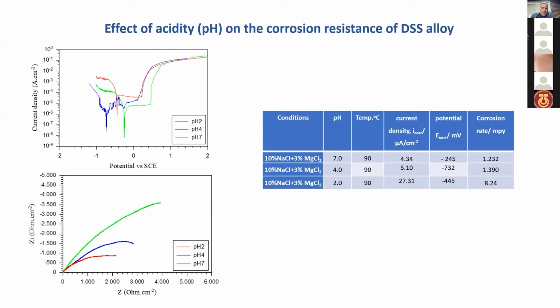Now we go to the second parameter, the effect of the pH or the acidity on the corrosion resistance of the duplex stainless steel. It was reported in a previous study that the corrosion in the magnesium chloride solution is higher than the sodium chloride due to the relatively high viscosity compared to the sodium chloride solution. And because of multiple operating environments and to cover the maximum possible of the influencing surrounding environment factors, it is necessary to study the effect of a mixture of these two solutions on the corrosion performance under relatively high temperatures and multiple pH values. So the samples were tested in 10% sodium chloride solution with 3% magnesium chloride added at pH 7, 4, and 2 at 90 degrees centigrade.